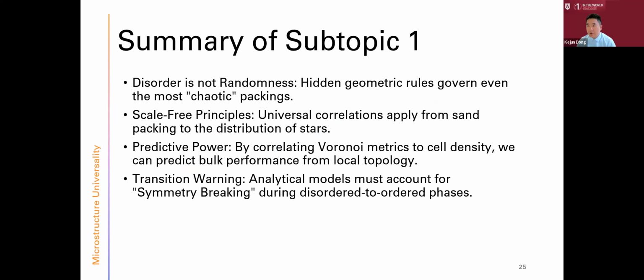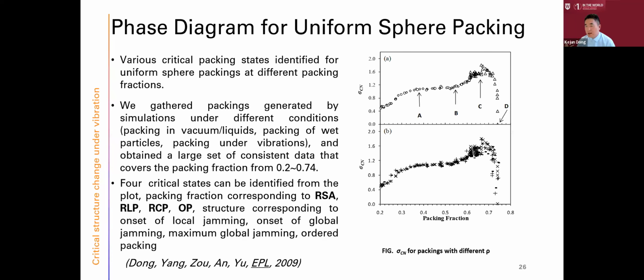Before that, I will do a summary of the first topic: disorder is not randomness. That means we can still find some hidden rules that help us to model the disordered structure. And importantly, if we can achieve the compression of information by using the packing fraction to predict those other microstructure parameters, that can help us to establish analytical models. But we can see if the structure really goes through a critical change, then for those laws we may need to consider the different phases, where we will have different correlations.